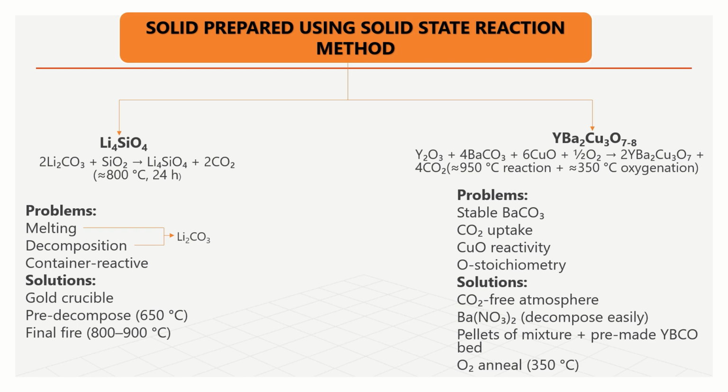The solution is to use gold crucibles. First, preheat to decompose the lithium carbonate at 650 degrees Celsius for a few hours, and then fire at 800 to 900 degrees Celsius overnight to get the final product.